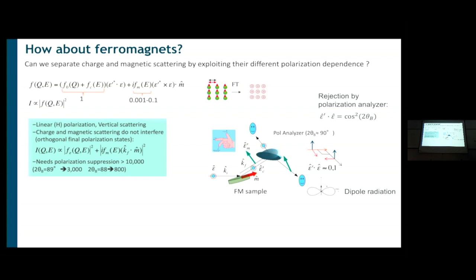So you need to add another crystal, a polarization analyzer, and diffract, because we don't have X-ray mirrors at high angles. We have to diffract from a crystal, and at 90 degrees, if you look at this, the charge scattering, let's say the polarization is out of plane, then it's not rotated. The magnetic scattering rotates the polarization, so it's pointing up. So if you scatter in the horizontal plane and you look directly perpendicular, you will see this, but the polarization from the charge scattering along this direction, you won't see it.